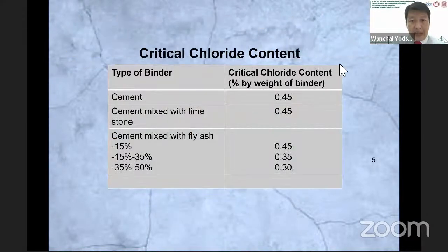For the chloride limit value, or the critical chloride content, they're set up in the standard depending on the type of binder. If the binder is only cement, the critical chloride content is 0.45% by weight of binder. And for the cement mixed with limestone, it's the same, equal to 0.45% by weight of binder.